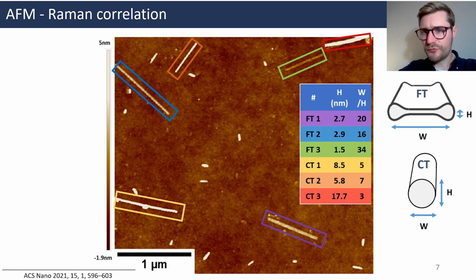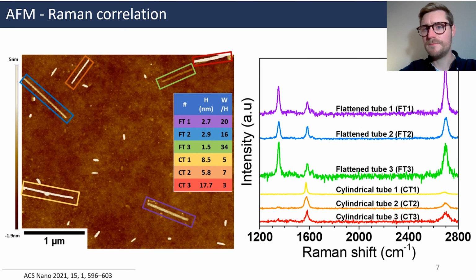We have here three cylindrical tubes and three flattened tubes. As I was telling you just before, we were able to attribute the spectrum of those single objects. We have then a direct comparison between the Raman response of cylindrical versus flattened tubes. I will actually show you that those spectra are very different. And here the spectra, normalized over the G-band.